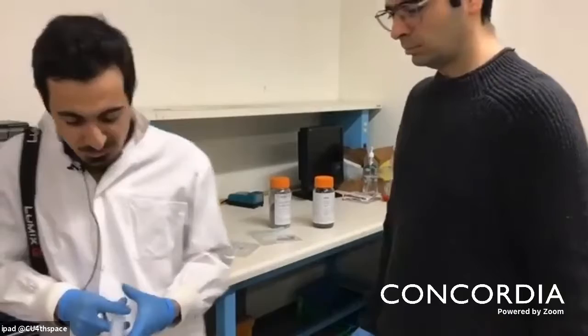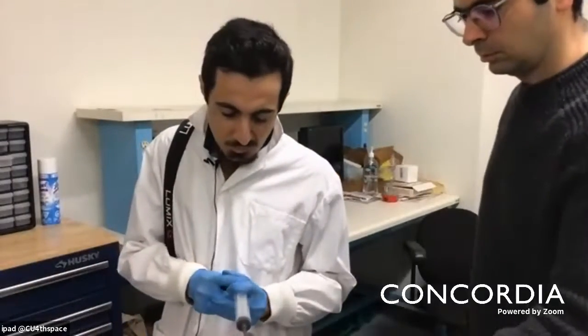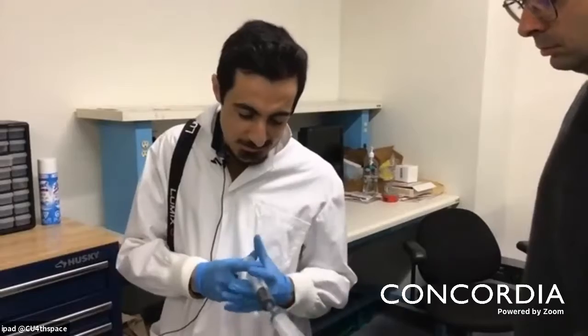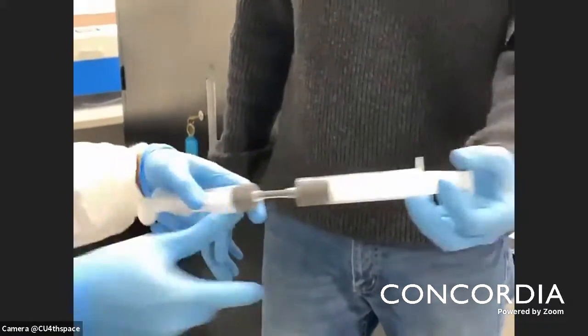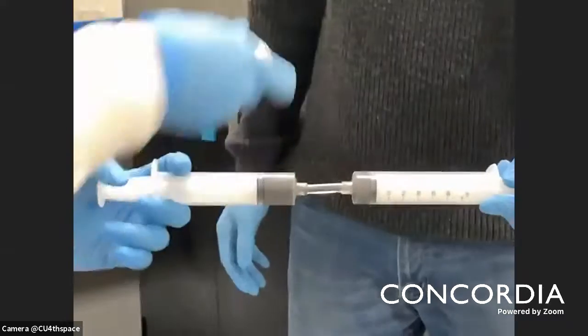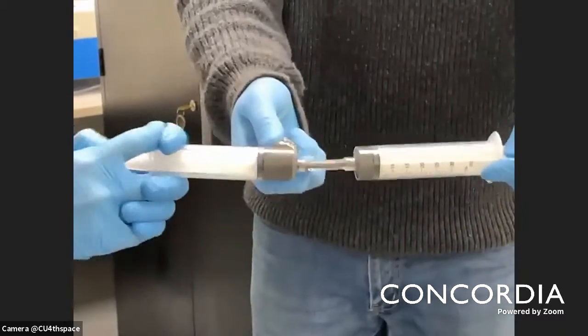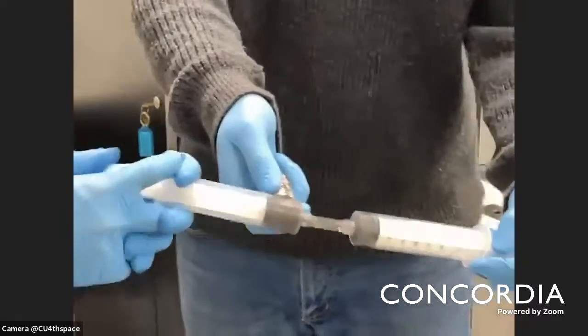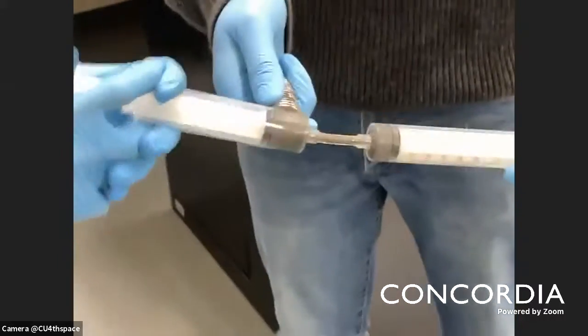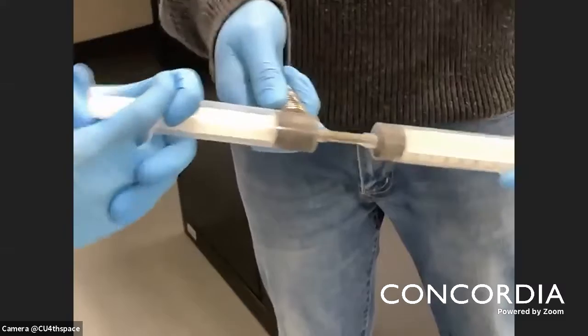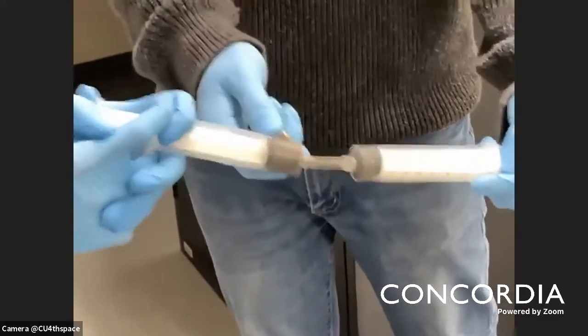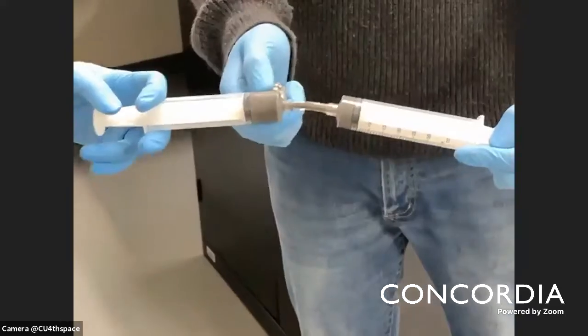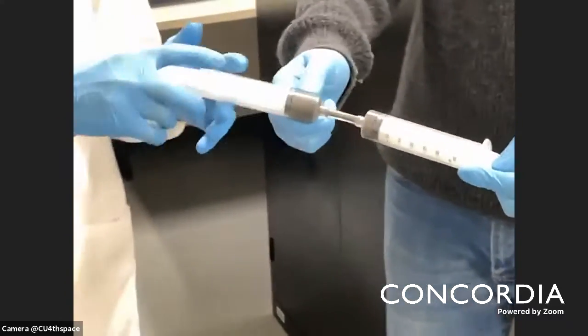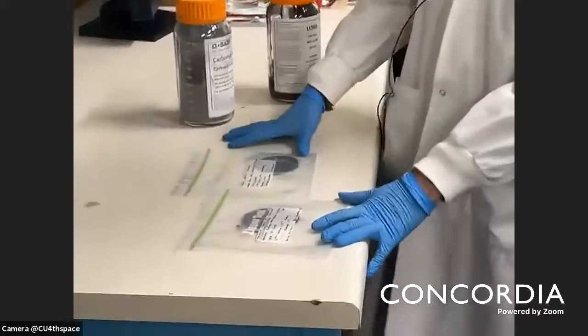You can see that you can push this plunger very easily. But when you apply the magnetic field, these materials become stiffer, and the viscosity will increase, and you cannot push it very easily. You need too much force, and this is one of the applications in MR dampers for suppressing vibrations. And here, this is the MR elastomer, the second type.